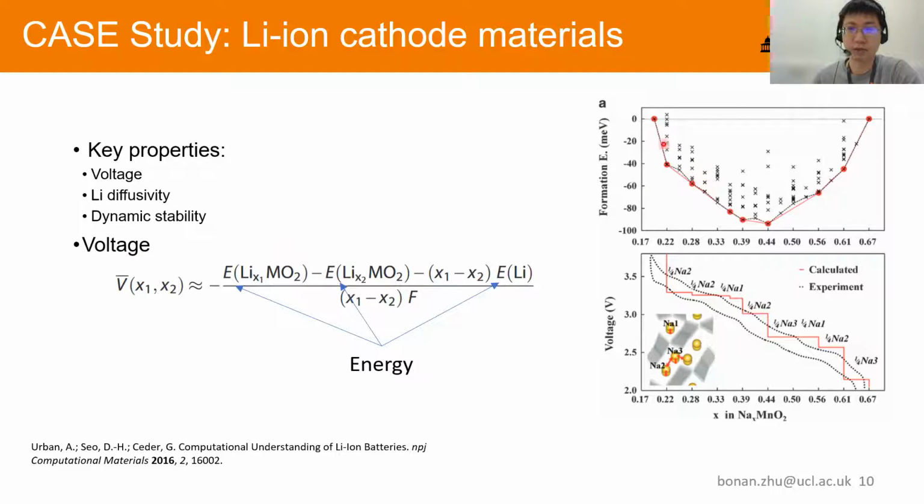But essentially, by calculating the energy of many different delithiation levels, you can form this convex hull. And then from the convex hull, you can extract these voltage profiles, which in many cases actually agree with the experiment very well.